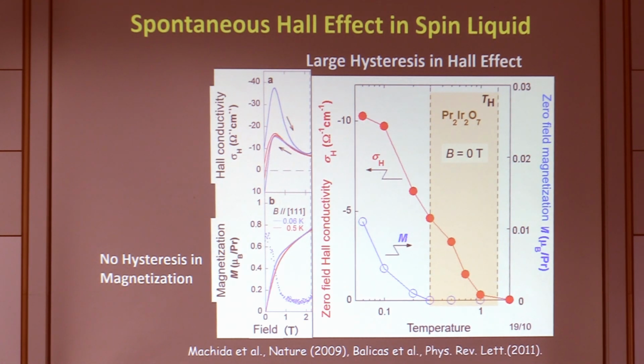And in fact, we found that this magnetization is just paramagnetic-like. There is no hysteresis. However, if you take the Hall conductivity, you see a very large hysteresis. Therefore, it indicates a spontaneous Hall effect in a spin liquid. So this was quite surprising. At that point, we didn't have any theoretical understanding, as Weyl metal was not yet predicted. But we found there has to be a large Berry curvature in momentum space.